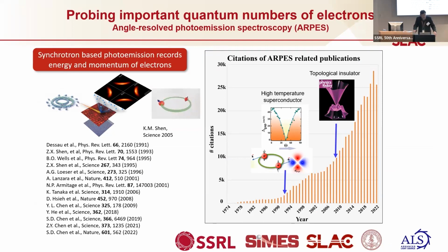In this sort of experiment, for this audience, we use the photoelectric effect, use a synchrotron light source, eject electrons from the surface, then you measure the energy and the momentum of those electrons. To the right-hand side are the citations of the papers over the period of time. And you can see that there's a very dramatic growth of that. One of the important milestones or inflection points was the discovery of the D-wave superconducting gap structure in the early 90s.